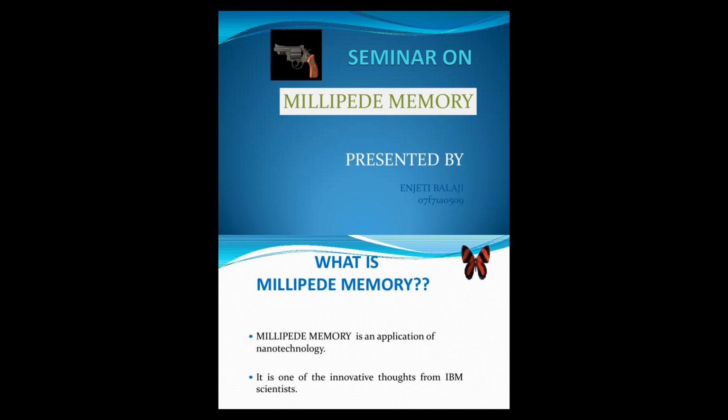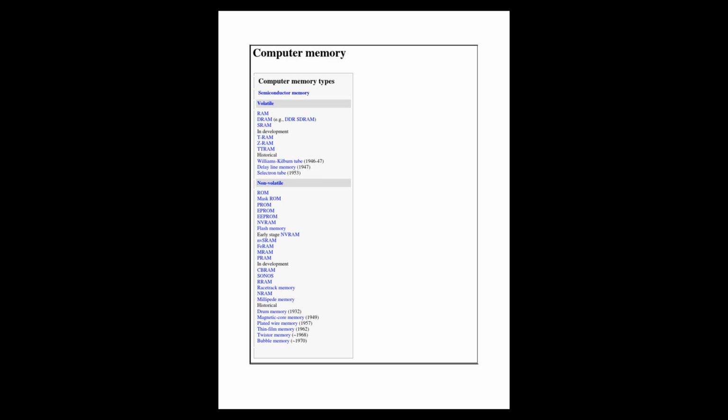First devices. The earliest generation Millipede devices used probes 10 nanometers in diameter and 70 nanometers in length, producing pits about 40 nanometers in diameter on fields 92 micrometers by 92 micrometers arranged in a 32 by 32 grid. The resulting 3 mm by 3 mm chip stores 500 megabits of data or 62.5 megabytes, resulting in an areal density, the number of bits per square inch, on the order of 200 gigabits per square inch.